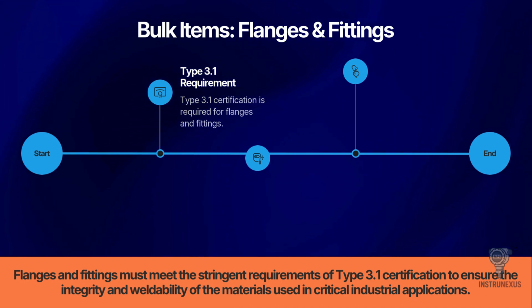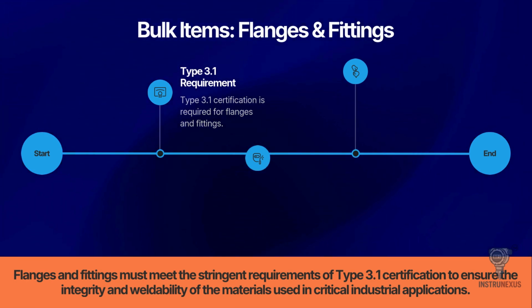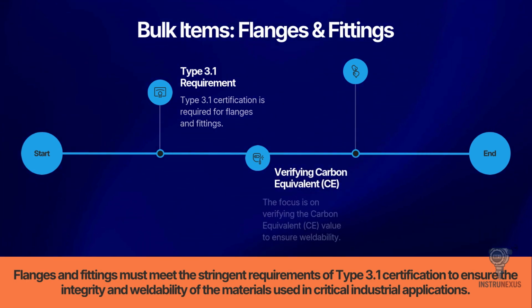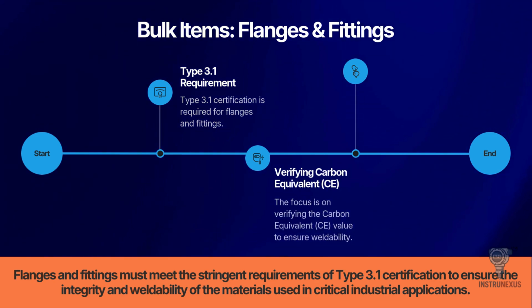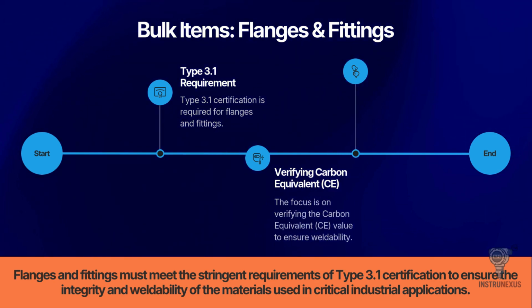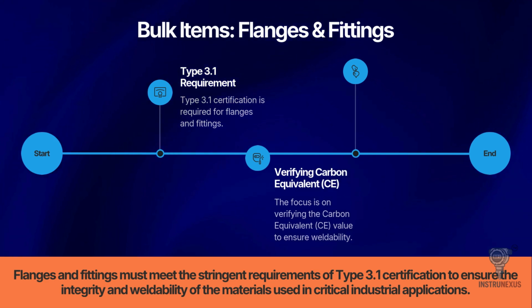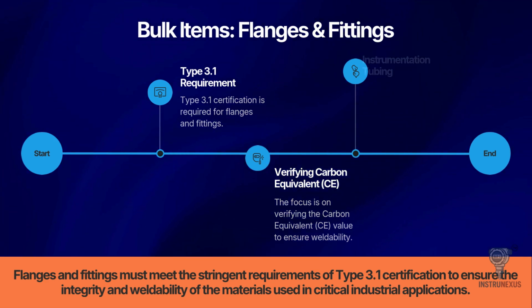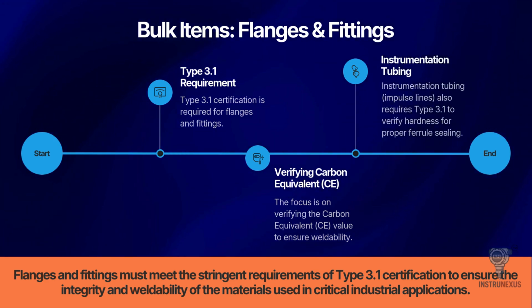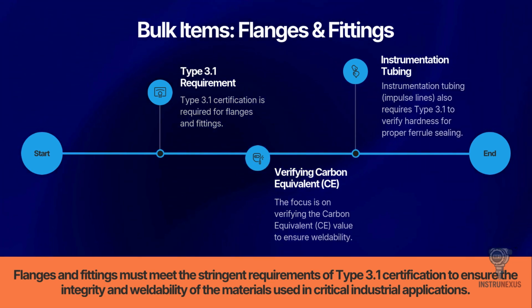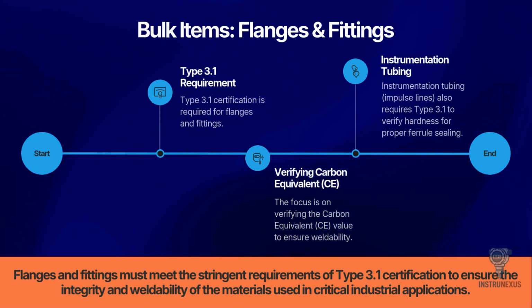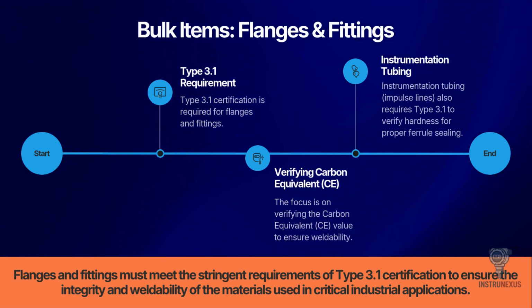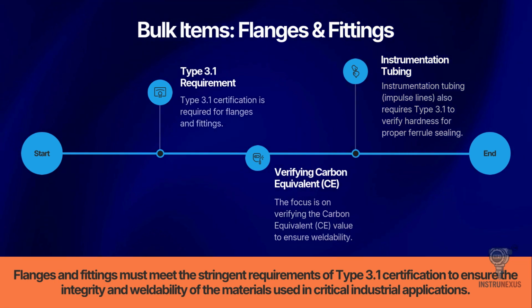Beyond just chemistry, the focus here is often on the carbon equivalent, CE, value. We need to verify this value to ensure the weldability of the fittings. If the carbon equivalent is too high, you risk cracking during welding. Also, don't forget instrumentation tubing. Impulse lines require Type 3.1 not just for chemistry, but to verify hardness. If the tubing is too hard, the ferrules won't seal properly, leading to leaks.